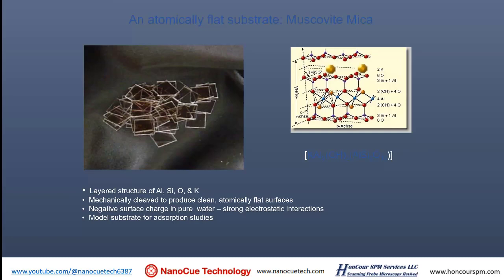And because the surface of mica is just being exposed to the environment, it is clean. It's guaranteed clean, atomically, molecular level clean. So when you clean the mica, it is clean, at least for a certain time. Very flat and very clean. So you can use that substrate to put your sample on, immobilize a sample.